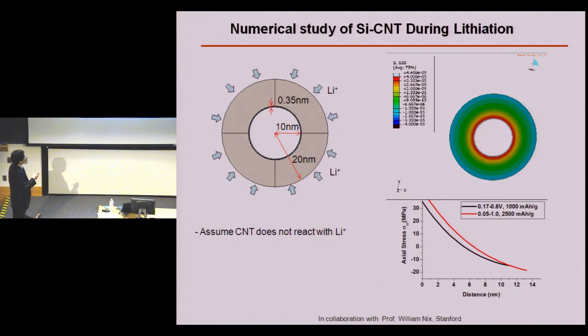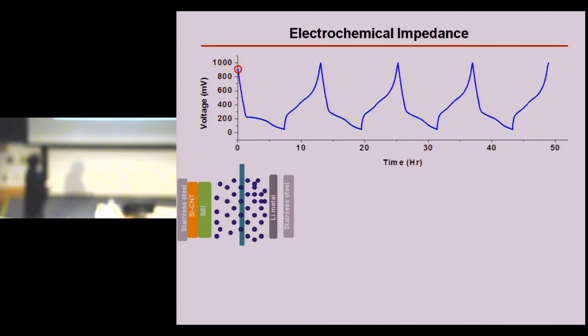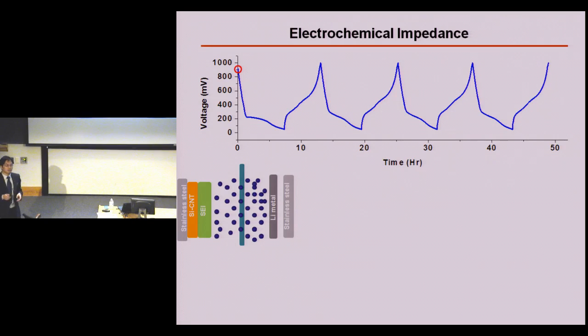And we believe that this huge stress building up at this interface could explain why silicon starts to break during this lithiation process. So electrochemical impedance measurement is very important for us to understand the transport of the lithium as well as the electron inside the structure.